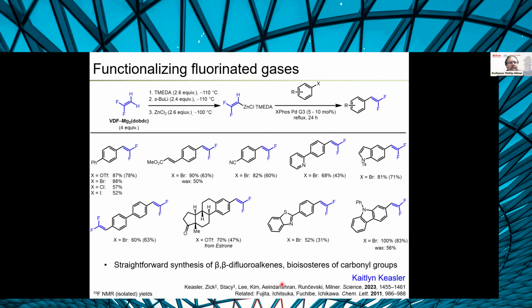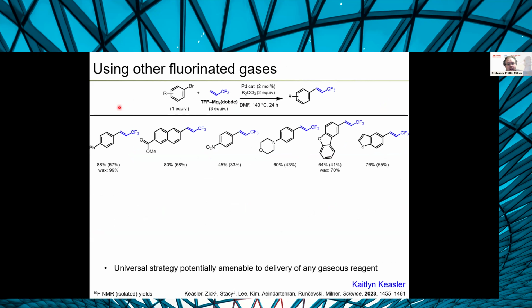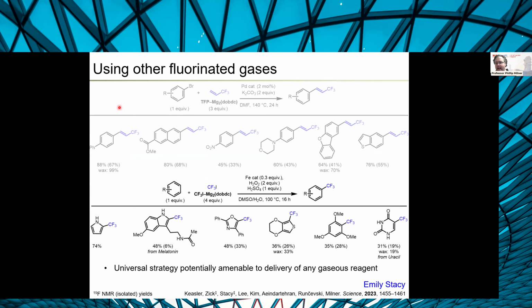So we found that for vinylidene fluoride, we can also deprotonate it using s-butyllithium and transmetallate to zinc to make the zinc reagent here, which engages in a palladium catalyzed Negishi coupling to make these beta-beta difluorostyrenes here with a pretty good functional group scope. So this is a way that we can actually functionalize both ends of VDF, either this carbon or this carbon. We also were able to use trifluoropropene here to do a Heck-like coupling to make these trifluoromethylated alkenes, and trifluoromethyl iodide to make also trifluoromethylated compounds under these Fenton-like conditions.